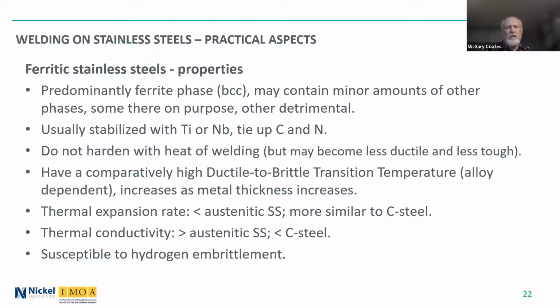The thermal expansion rate is less than austenitic stainless steel, more similar to carbon steel, a little bit higher than carbon steel, but much, much closer to that than the austenitics. The thermal conductivity, the heat transfer through the material, is much higher than an austenitic stainless steel, but still significantly lower than a carbon steel. And they're susceptible to hydrogen embrittlement, and I mention that primarily because if you have moisture present, whether on the base material or on the welding electrode, you can get hydrogen released, and you can get an embrittled weld.